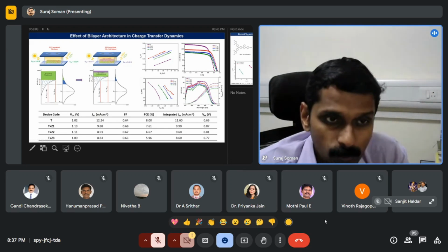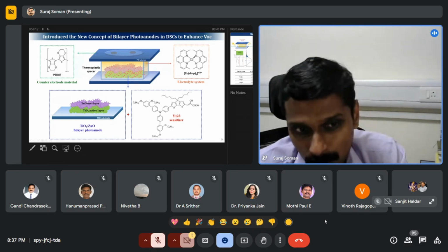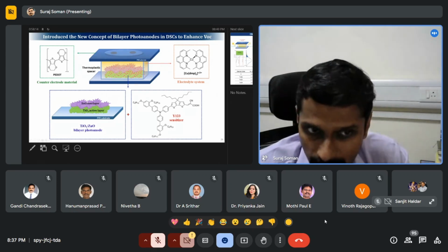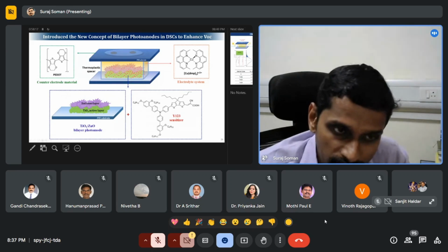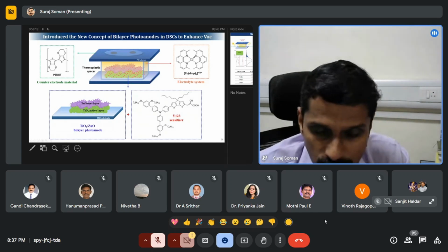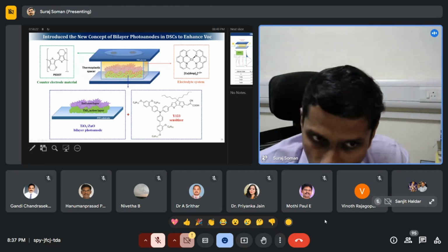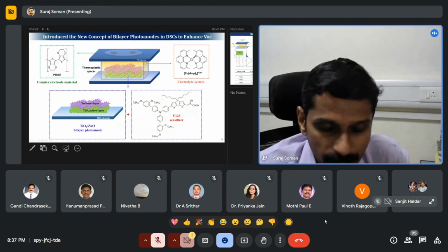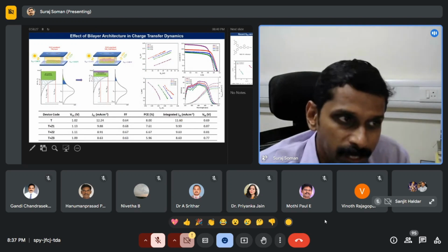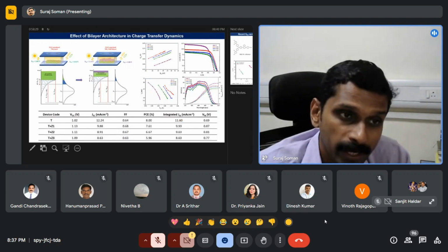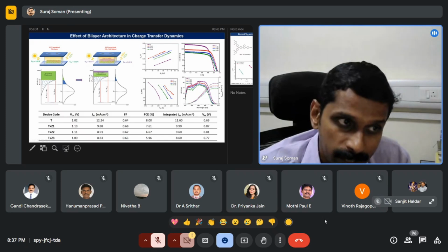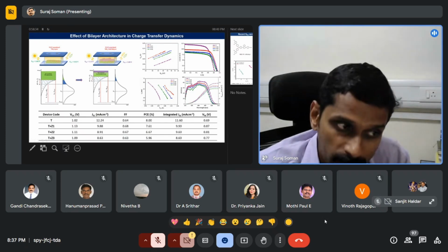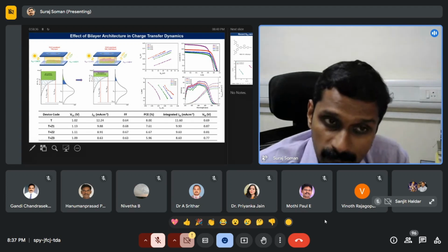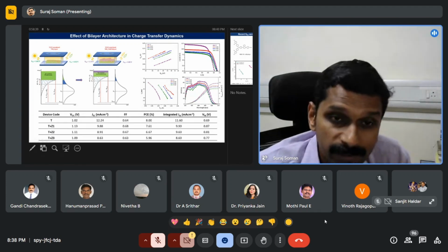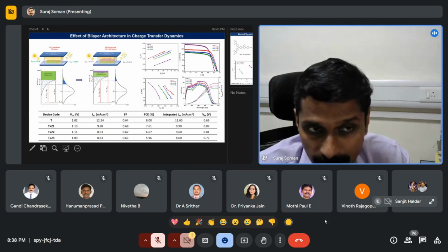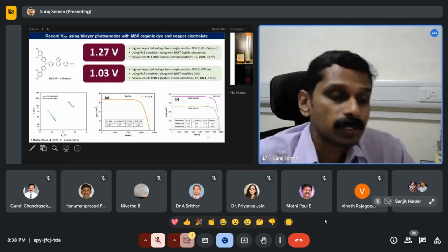So this particular work was initially done with only one single molecule, which is a standard organic dye based on triphenylamine, where you are having a triphenylamine as the donor, a pi spacer, and an acid functionality. Okay, so this dye is called Y123 dye. At this particular point we realized that the bilayer electrode has a very huge impact: there is a negative shift in conduction band that automatically increases your voltage. At the same time, there is an improvement in the lifetime. So can we try something very unique from the molecular side, which can further improve this particular aspect?